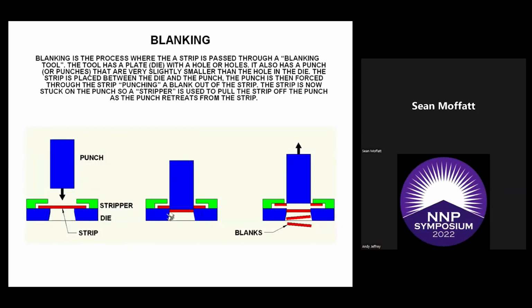Now we're going to move on to blanking. Blanking is a process where the strip is passed through a blanking tool. The tool has a plate known as a die with a hole or holes in it. It also has a punch or punches to match the number of holes in the die. They're just very slightly smaller than the hole in the die. The strip is placed between the die and the punch, and the punch is then forced through the strip, punching a blank out of the strip. The strip is now stuck on the punch, so a stripper is used to pull the strip off the punch as the punch retreats.